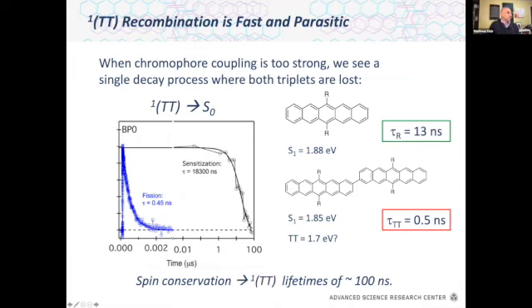I won't give you all the details, but if we take a chromophore like this, where the two chromophores are directly linked, and compare the lifetime of the triplet pair in this dimer to the lifetime of the singlet in this monomer, the triplet pair actually shortens by a factor of 20, actually more than 20. So what we've actually done is created a triplet that decays faster than the singlet. So that's certainly not bad. No, certainly not good, sorry.